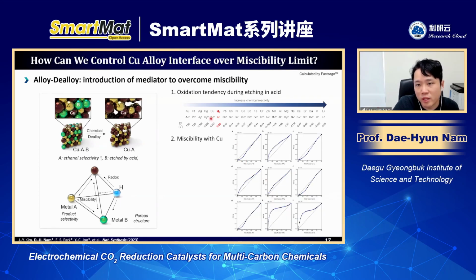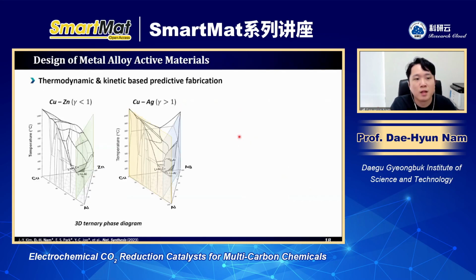So based on this point of view, with the calculation for a whole series of metallic elements, we found that zinc is easy to mix with copper, and silver is immiscible with copper. It means it doesn't mix. So to study metal alloy systems, we categorize zinc and copper in terms of